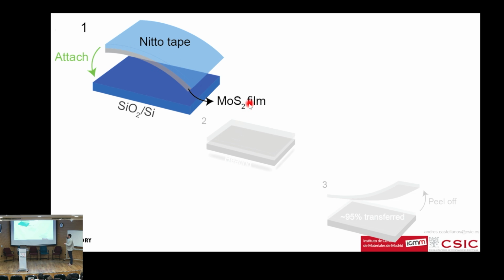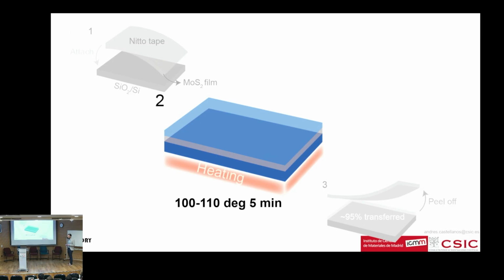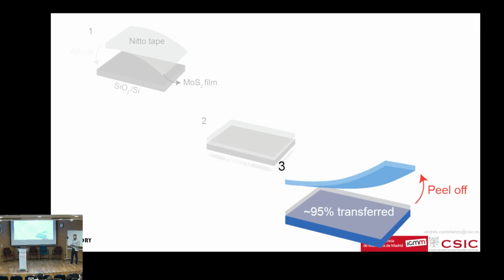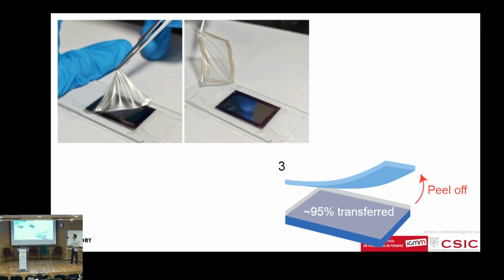In this case, we have a molybdenum disulfide film. We attach it to the target substrate and heat it for 5 minutes at 100 degrees. Then when we peel off, almost all the flakes on the tape get transferred onto the surface. This peeling off process looks a little bit like this. You see here, this rectangle is where the flakes have been transferred to this silicon oxide chip, and the tape has an empty rectangle where the flakes were transferred.